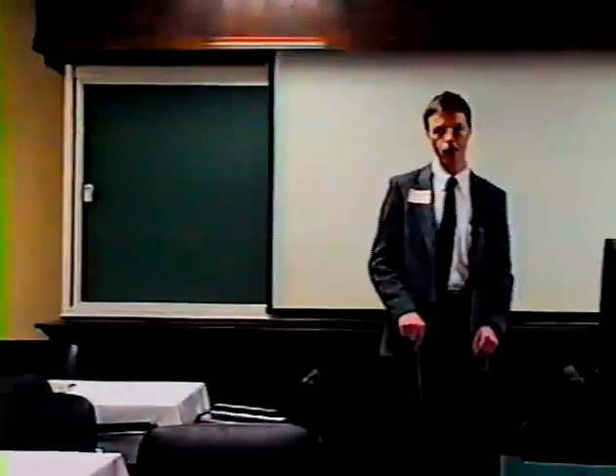There's time for discussion, questions. Go ahead. Okay, George, I was interested in your comparison of your platinum 2 catalyst with platinum tin organometallic. In those compounds, platinum is 2+. In your catalyst, when you're doing the EXAFS, did you see, some people claim that the strong interaction of platinum with the support yields a platinum partially positive. Now, did you see any evidence of this in your EXAFS work?